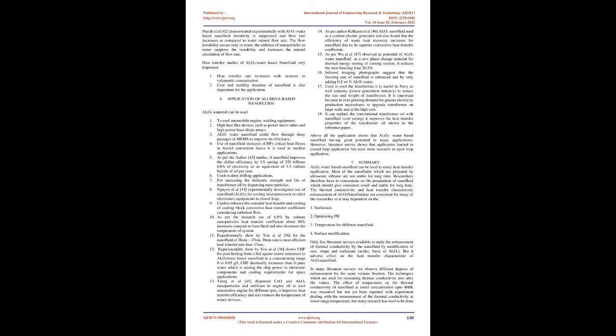Farajalahi et al. 39 studied water Al2O3 and TiO2/water nanofluid in a shell and tube heat exchanger with turbulent flow and showed that at optimum concentration of nanoparticles in water, TiO2/water nanofluid has better heat transfer characteristics than Al2O3/water-based nanofluid, and an optimum concentration of nanoparticles in water exists. The author also shows that the heat transfer characteristic of Al2O3/water nanofluid increases with increased concentration.